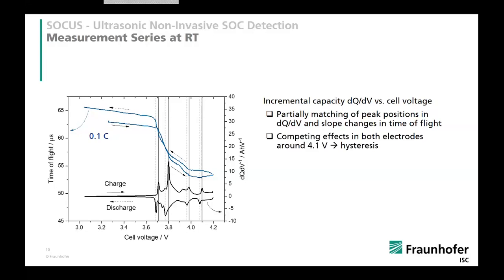On the very first slides, I mentioned that the cathode does not change so much in its mechanical properties. However, at 4.1 volt, where nearly 0.5 lithium is depleted from the cobalt oxide lattice, there is a change in the crystal lattice along the H1 axis reported, and this has an effect on the mechanical properties, and combined with the strong change of the anode graphite parameters, we assume that this is the cause of this hysteresis, which we want to further test.